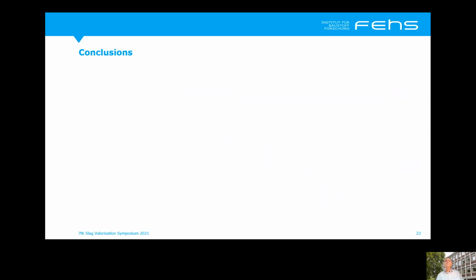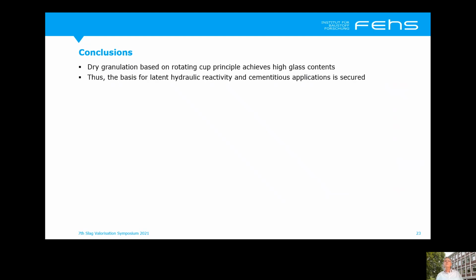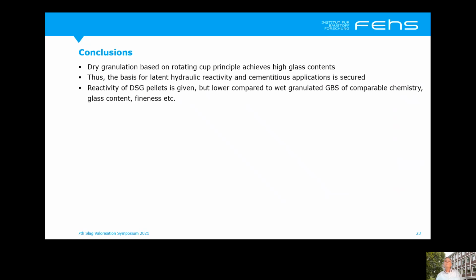Thus, we came to the following conclusions. The dry granulation based on the rotating cup principle achieves high glass contents, very high glass contents. Thus, the basis for the latent hydraulic reactivity and the cementitious applications is secured. However, the reactivity of the DSG pellets is given but lower compared to wet granulated GBS of a comparable chemistry, glass content, fineness, etc.